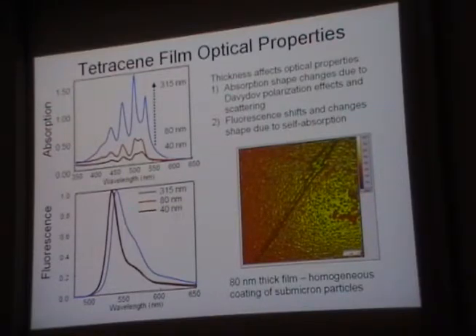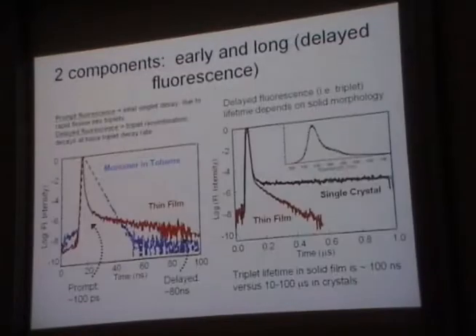The best way to avoid those is to make very, very thin samples. But the problem with very thin samples is you get very low signals. With fluorescence, that's not a problem, because you're always rolling in signal with fluorescence. So we'll start out with fluorescence. This is just monomeric tetracene in solution. We're going to do a lot of comparisons between the solid and the monomer because that's the best way that I, as a chemist, can sort of keep sane.